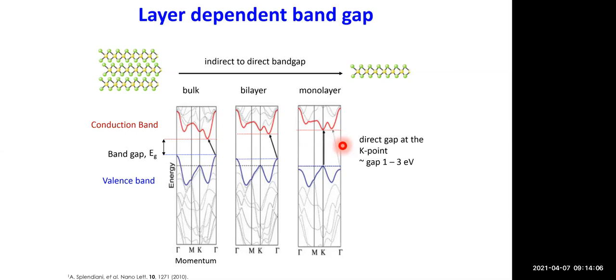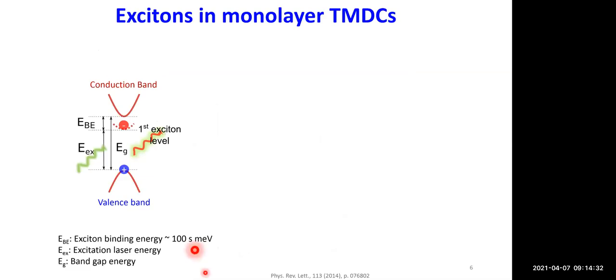So any kind of optical absorption or emission process is enhanced for the case of these monolayers. For example, you can absorb around 20% of the incident light at the excitonic resonances of these materials, and these materials have also shown a unity quantum yield in some PL processes as well. So we utilize this enhancement and study excitons in these materials.